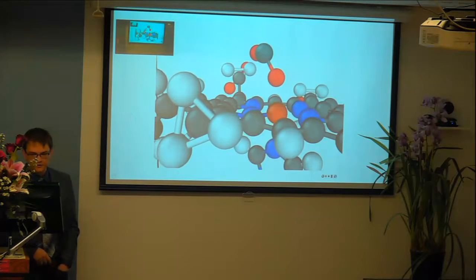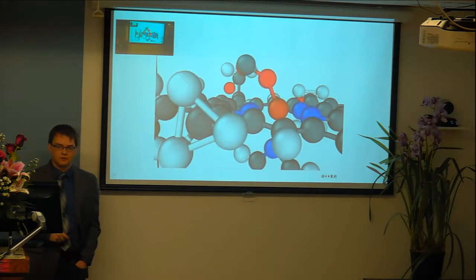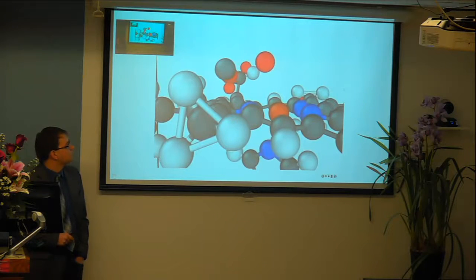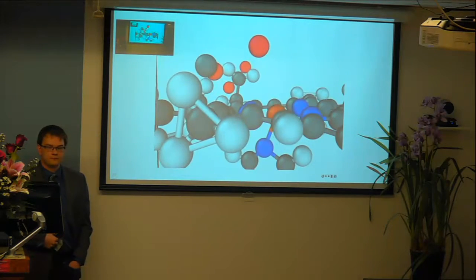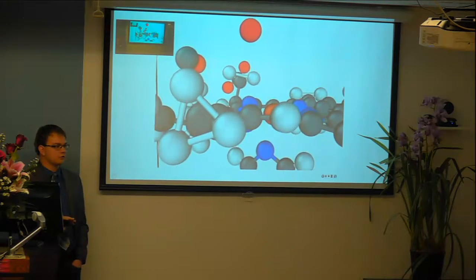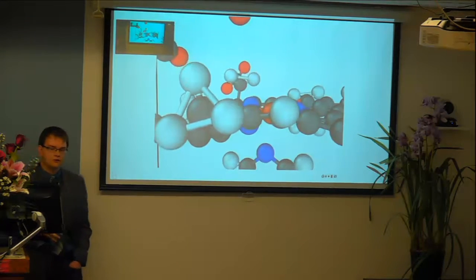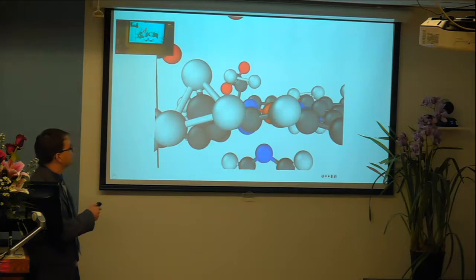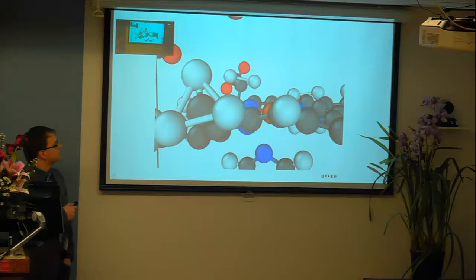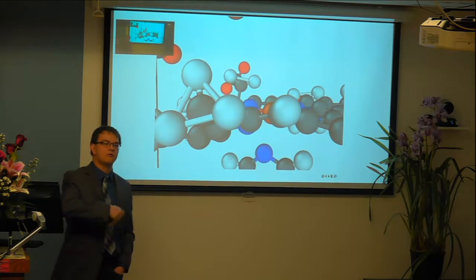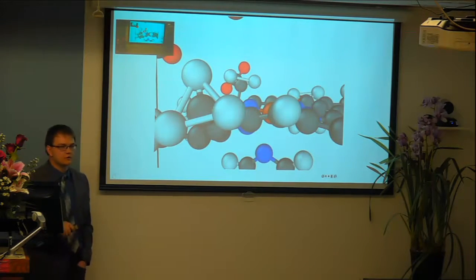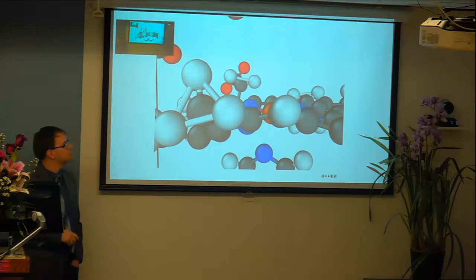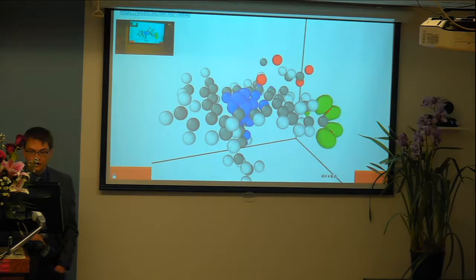So here we have 60 degrees again. It did not work out because this one was at a higher velocity. And so it's kind of a double-edged sword. You can't have too high a velocity because it'll bounce off and possibly break the bond in and of itself, but this oxygen won't attach. But too low, it'll bounce back or reflect off of the potential energy surface. So it's a real kind of fine-tuning to get this right.